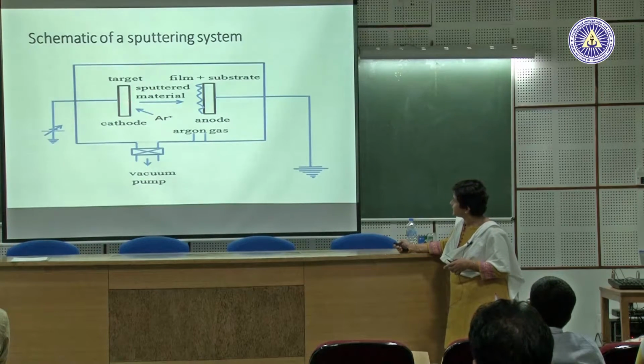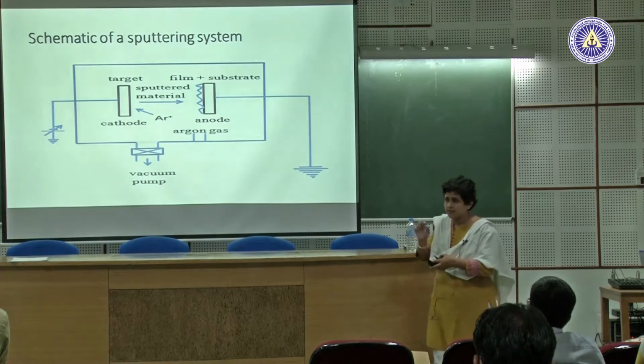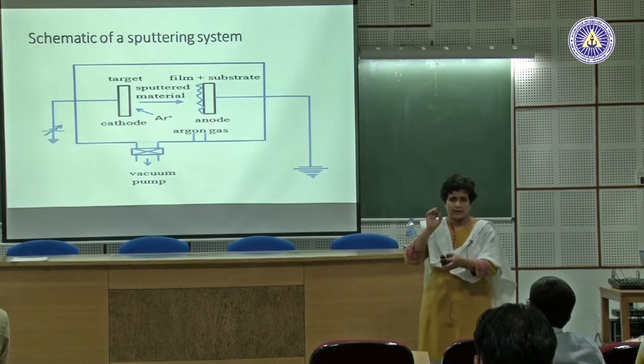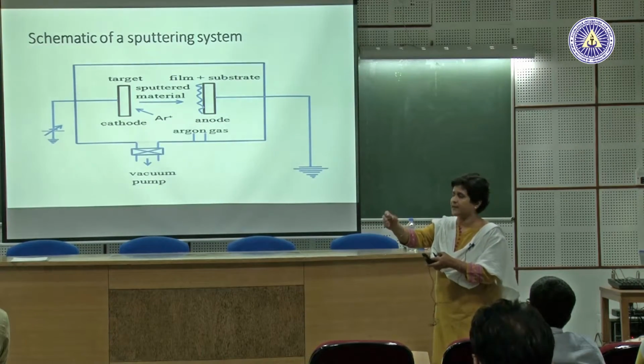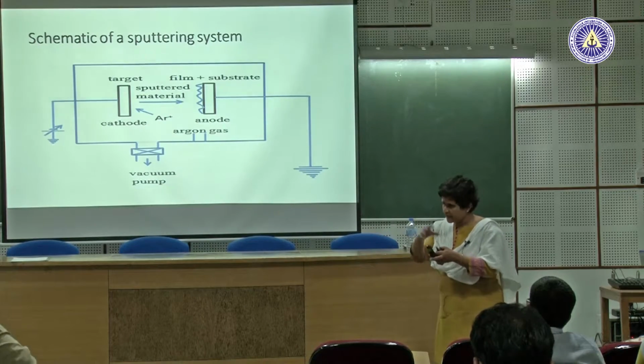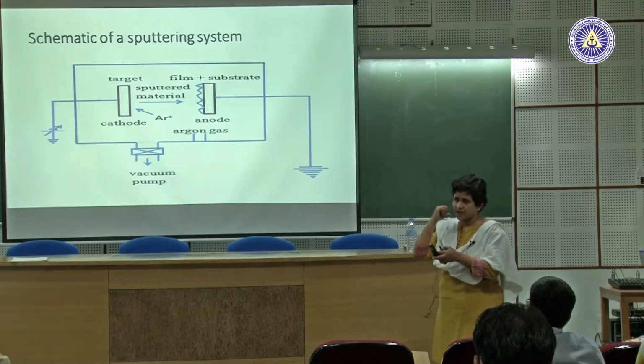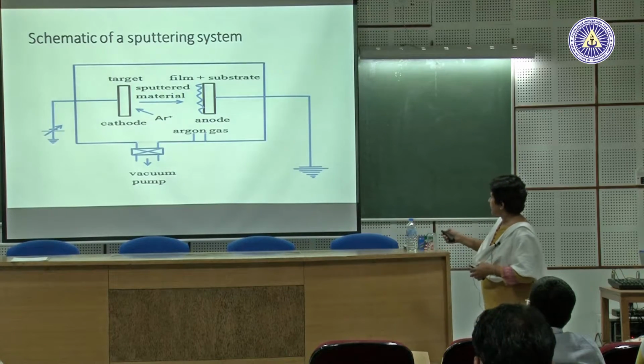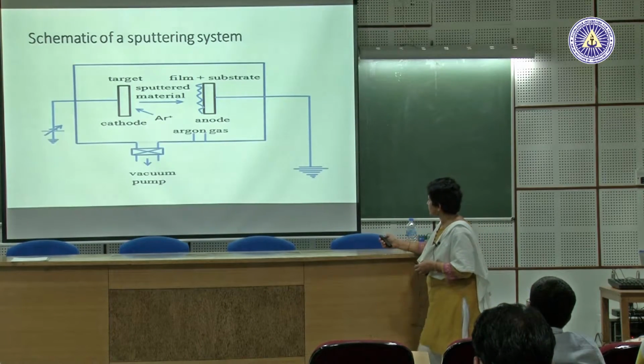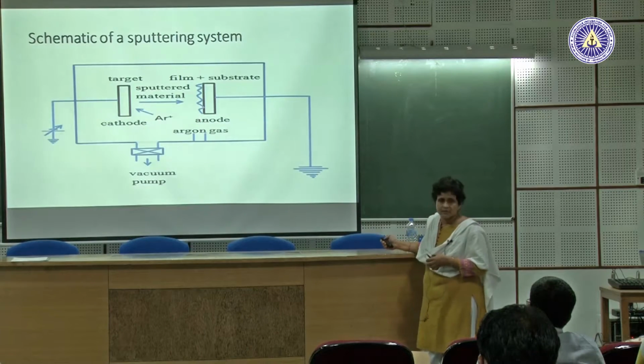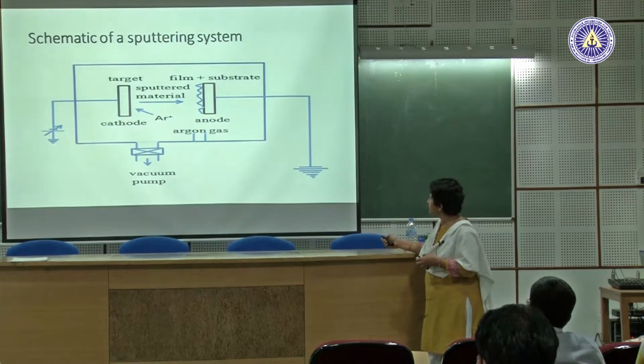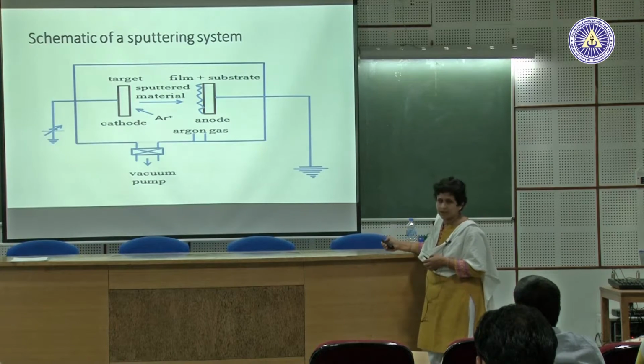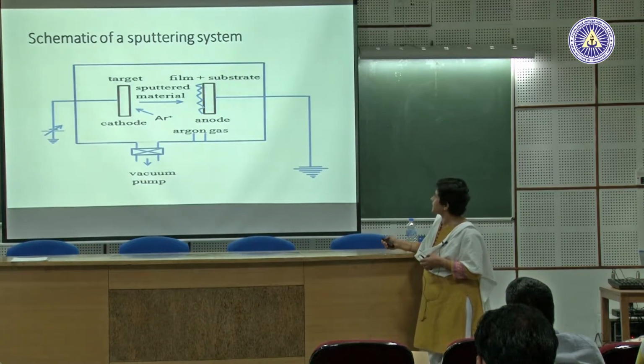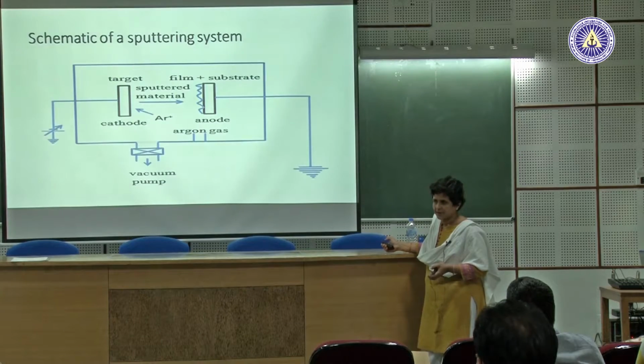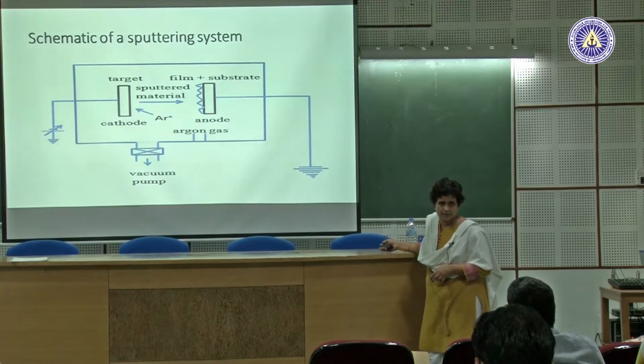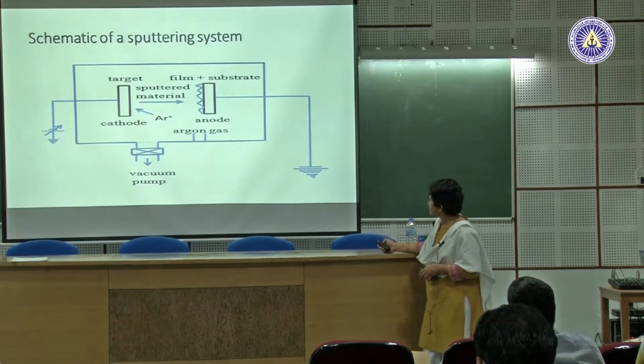The sputtered material, it's like a billiards ball, the atoms are coming and hitting another target. Based on the kinematics of it, that material will come out in a particular direction, and you need to place your substrate such that the sputtered material is received by the substrate, and then this material will form the film on this substrate. Okay. So, this material is sputtered and the film is being formed here. That is how the sputtering takes place in the basic concepts. Okay. Now,